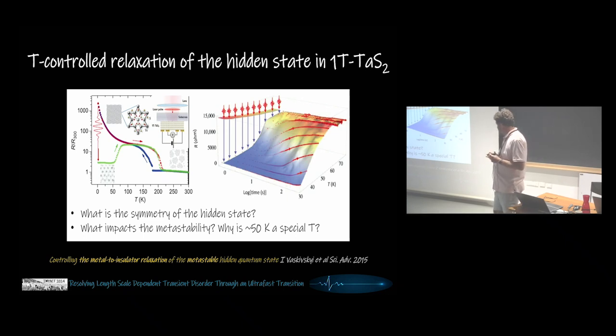50 Kelvin. You can also do the switching at higher temperatures, but then that metastable, that hidden state is no longer metastable. It actually very quickly decays. And so one of the questions that one might ask is, why is quote-unquote 50 Kelvin special in this system? And what is the symmetry of this hidden state? Is there a difference in the states that you are pumping on, or is there a difference in the states that you are actually ending up in?